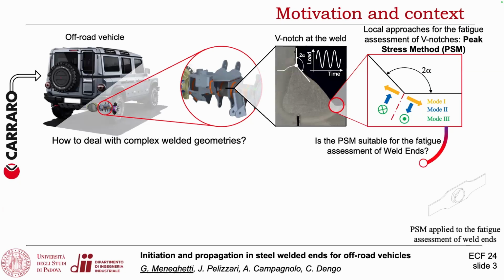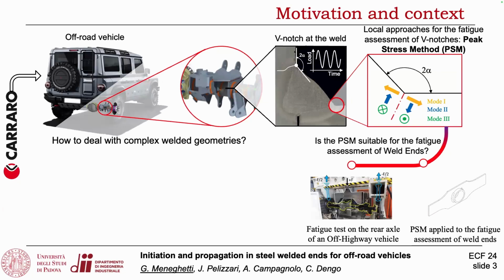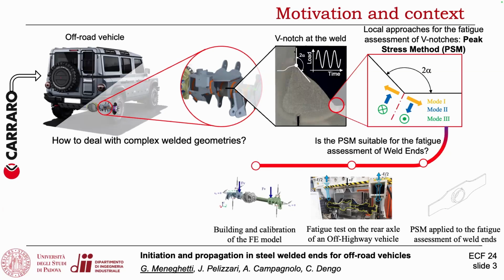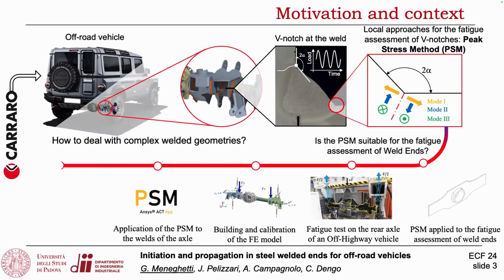So with these research questions in mind, we followed parallel tracks: fatigue testing with laboratory specimens and intermediate welds, but also fatigue tests on full-scale structures. Then we calibrated the finite element model with an appropriate prototype instrumented with strain gauges, and we applied the peak stress method, which is now automated in ANSYS.